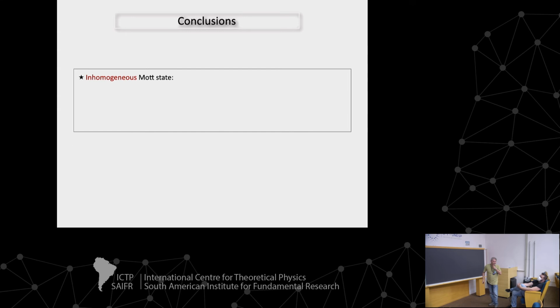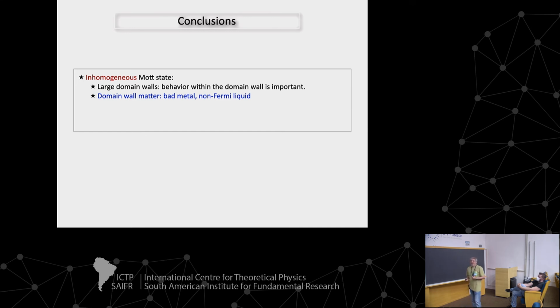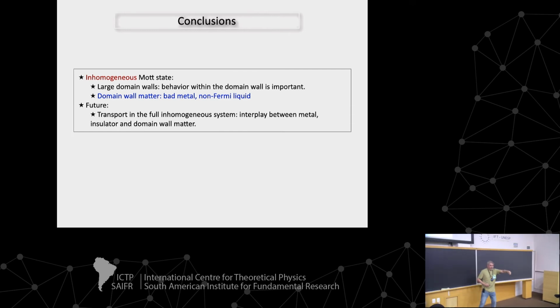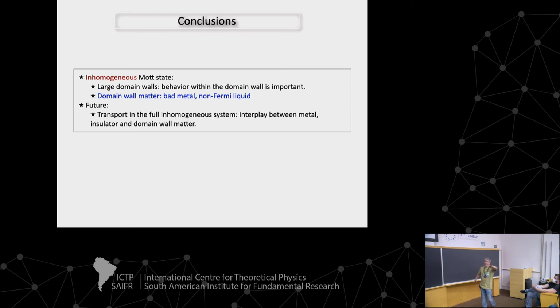So in conclusion here, I think I went over my time a little bit. I talked about the inhomogeneous Mott state with large domain walls, and I focused on the physics of the domain wall matter, where I tried to convince you that this is a bad metal, or a non-Fermi liquid, as it's called. And in the future, of course, the challenge is to calculate transport for the full inhomogeneous metal, which I didn't do. I calculated sort of the local conductivity. I looked at the metal bubble, at the insulating bubble and domain wall, but I didn't calculate the bulk conductivity of this inhomogeneous system. This is a real challenge, even within this theory, and this is work for the future. Okay, that's it. Thank you.